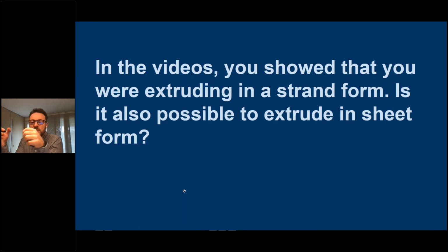We have a sheet extrusion die. You can also call it a film die, but normally the thickness is not too thin. For rubbers, it's thick, let's say 2 millimeters, 3 millimeters. Even thicker we can arrange. So you can make strips out of rubbers, and you can extrude that strip directly into a container, or as I showed in the videos, we also have a mini conveyor belt. You can just extrude that strip onto the conveyor belt and take it for further analysis.